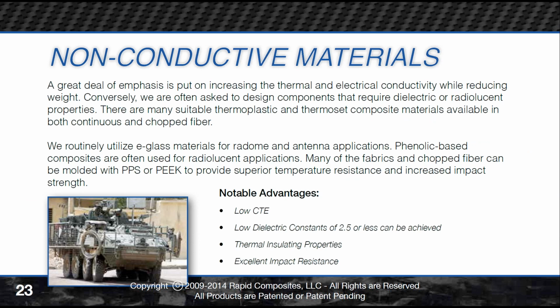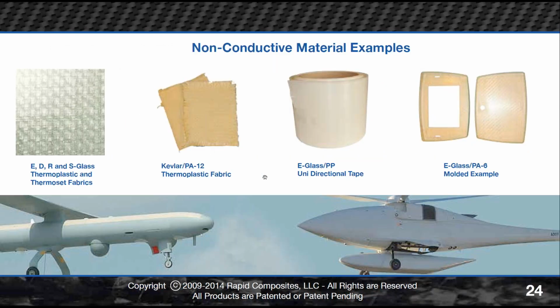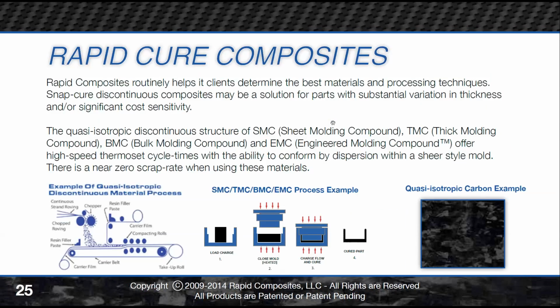We also conversely work with a lot of non-conductive materials. So we have materials like the ones you see here, in some cases like the e-glass polypropylene right here. It's got a dielectric constant of 2.5 or less. So it's a very good durable material that we can mold extremely fast for radomes and belly pods and antenna caps and that kind of thing. And in fact, in some cases, we can actually combine it and insert mold it into other materials that are more conductive. So for instance, we might shield around the perimeter and then have just one little spot that we plug into the mold that is non-conductive and radiolucent.